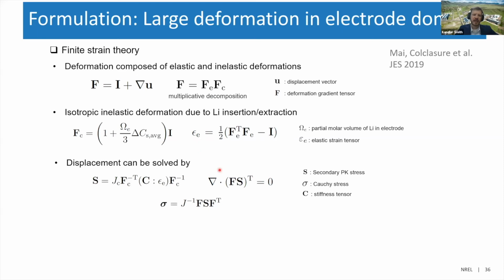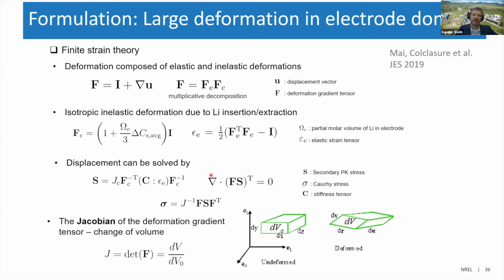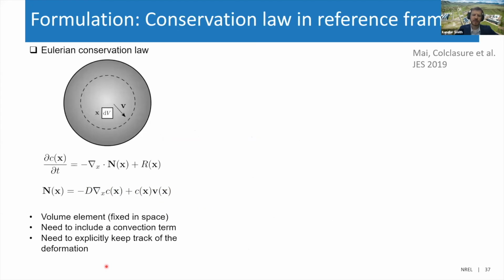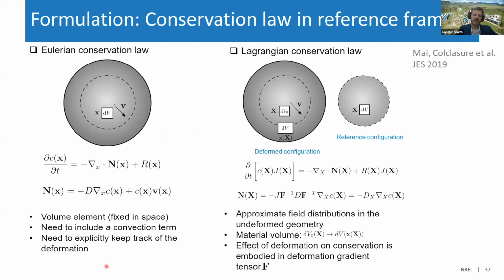And then another factor that we have is the Jacobian of the deformation gradient. This is something that turns up quite a bit in the governing equations, and I only have some small examples of this. But this Jacobian of the deformation tensor shows up differently whether you use an Eulerian conservation frame or if you use a Lagrangian conservation frame. And we've chosen the Lagrangian conservation frame. So as we have volume expansion and deformation, we are not remeshing this, just the mesh itself expands. And that's described by this deformation tensor as well as the Jacobian.